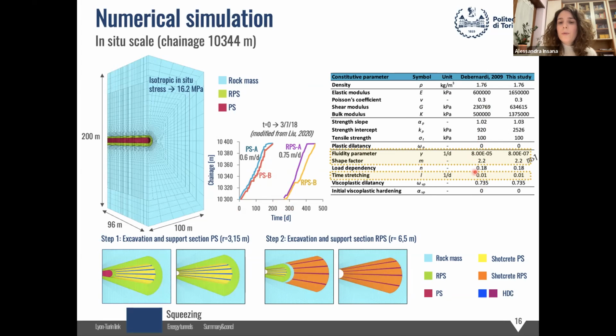So we had to change some parameters, and in particular, we kept constant N and omega VP because we believe that, given the fact that N is related to the deviatoric stress and omega VP is the ratio of volumetric to deviatoric plastic strength, they can stay the same. But the shape factor, the time scale, and the fluidity parameter are parameters that may change in situ. So we had to recalibrate them.